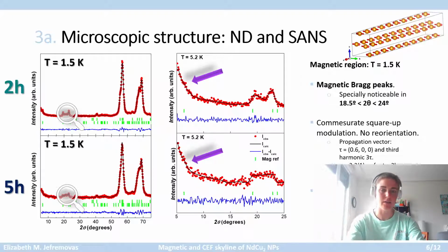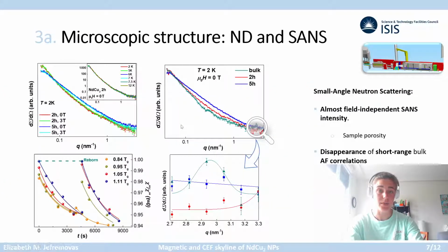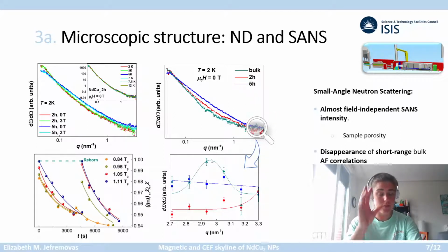whole antiferromagnetic range. And we also observe the existence of a rise in the low Q, low angle region, indicating the existence of interparticle correlations. So to further explore this interparticle correlation, we have performed small angle neutron scattering measurements. And what we observe is that whereas for the bulk alloy there is a clear peak near 3 nanometers^-1, the nanoparticles do not account for this peak, meaning that this additional correlation felt by the magnetic moments of the bulk alloy is not retained in the nanoparticles.